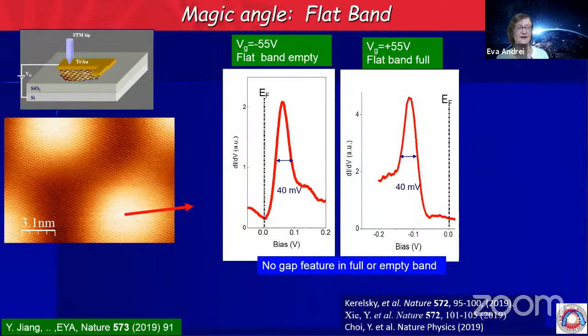The next thing that we did is look at the density of states, which is the dI/dV map. Since we now could move the Fermi energy because we have a gate voltage here, we first moved the Fermi energy way below this flat band. One of the advantages of STM, scanning tunneling microscopy and spectroscopy, is that you're not limited to the Fermi energy. Whereas with transport and ARPES, with most other techniques, you can only look at what's going on at the Fermi energy, or in ARPES only below the Fermi energy. We can actually scan the whole energy range.